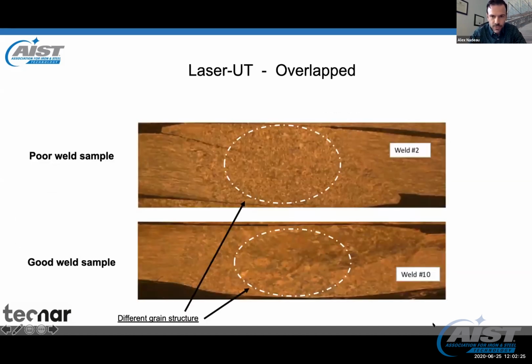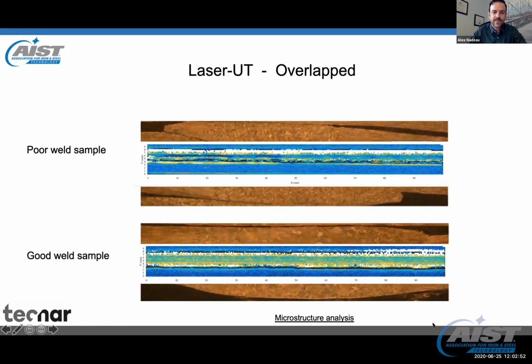If we look at microstructure, those are weld number 10 and number 2. So we could see that number 10 was a good weld. There's no cracks, and you can see with the eye that the grain structure is different. There was enough heat in there to have a very mature recrystallization. And for weld number 2, although there are visually cracks there, you can see how fine the grains are, and that this weld was not really hot and didn't have the chance to grow some nice grains. So it's in accordance with what the overlap method also provides. So it's a bit more advanced method.